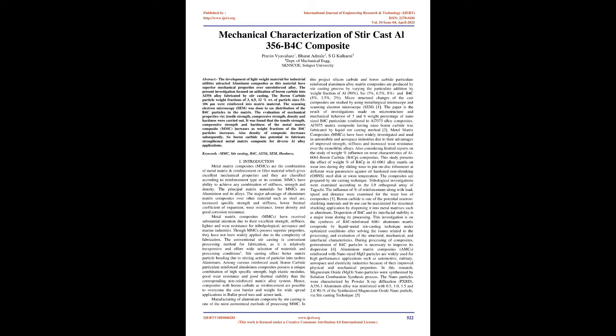The boron carbide particle weight fractions of 3, 6, 9, 12% weight, with particle sizes of 53 to 106 µm, were reinforced into the matrix material. Scanning electron microscopy, SEM, was done to see the distribution of the B4C particles in the matrix. The evaluation of mechanical properties, viz., tensile strength, compressive strength, density, and hardness, was carried out.